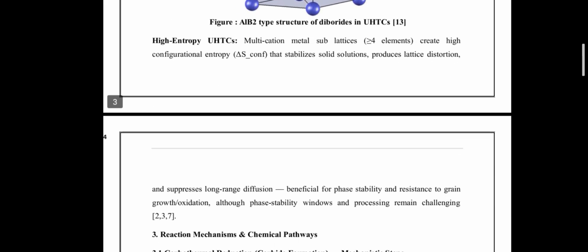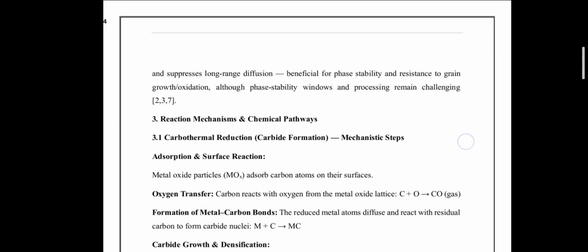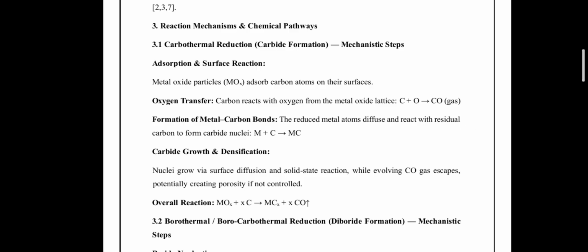Next are the high entropy ultra high temperature ceramics. High entropy ultra high temperature ceramics incorporate multiple metal cations on a single sublattice, increasing their configurational entropy and disorder. This leads to lattice distortion, suppressed diffusion, and improved phase stability, which can enhance oxidation resistance and grain growth control. Despite their promise, the processing and the phase stability window remain challenging in high entropy ultra high temperature ceramics. Let's move toward the reaction mechanisms and the chemical pathways.